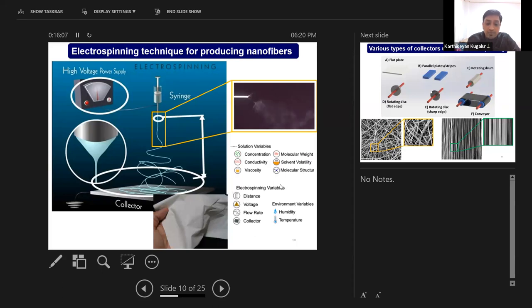Another main parameter, which contributes to the fiber diameter size reduction or increase, comes from the electrospinning variables, that is the distance between this needle and the plate and the voltage which you are applying. This is basically 20 to 30 kilovolts of voltage applied during the electrospinning process. When you change the distance between the tip and the target, or change the voltage, or change the flow rate of the solution, these can influence the fiber diameter. Similarly, the humidity and the temperature can also affect the fiber diameters.